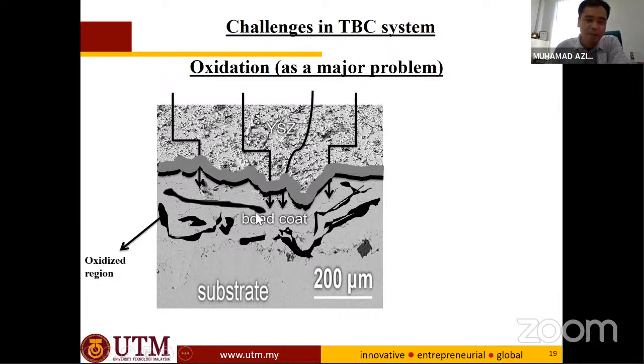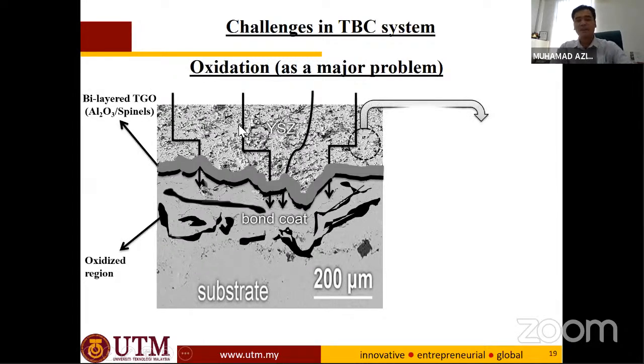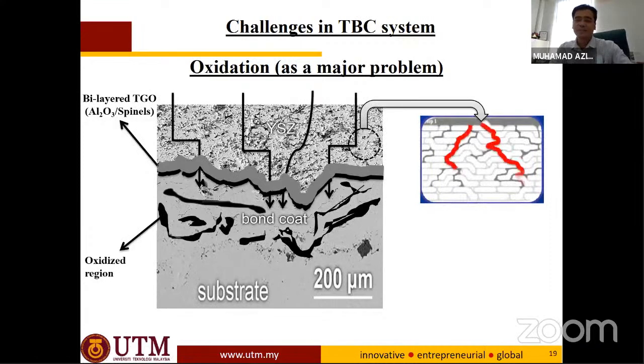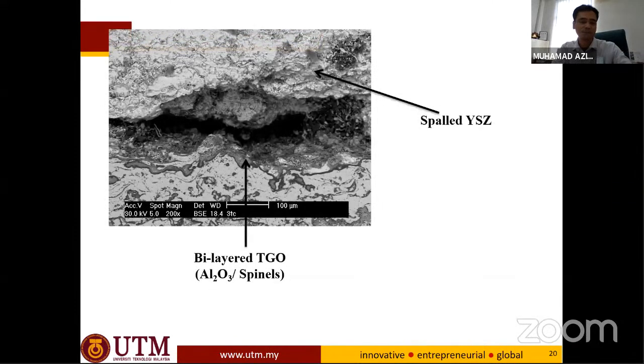So this can prevent the nickel from the bond coat going out, and then they create a layer of this, what we call compressive stress here. So how do we prevent this? We need to design the architecture here. Either we have another layer, or you seal the porous structure with something else. Okay, so this is the problem. You can see this is the pathway for oxygen diffusion, because of the nature of the YSZ, these are very porous.